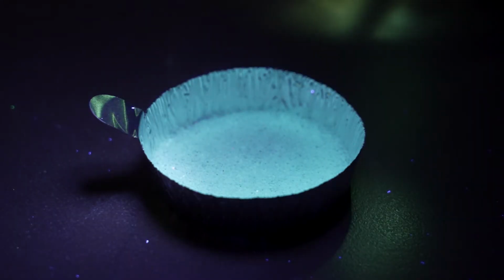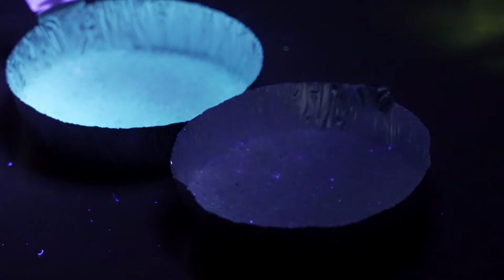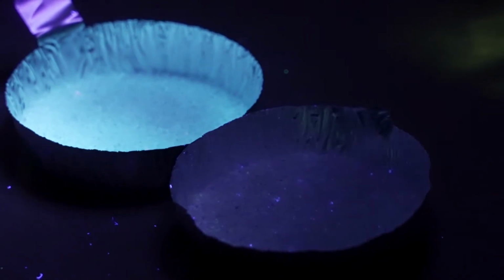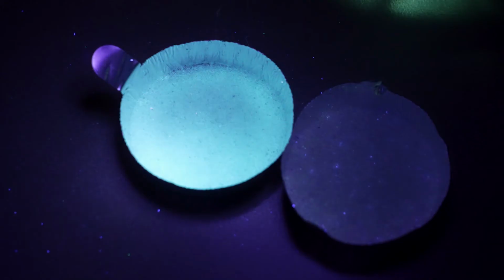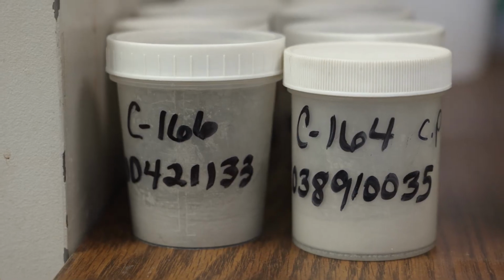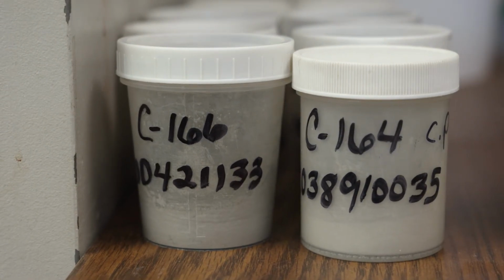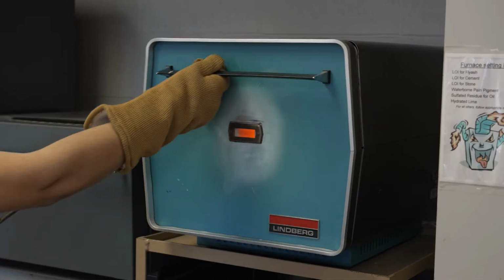We take the beads and we add a chemical called dansyl chloride, and that reacts with the coating. And that reaction causes a product that glows under UV light. So after the test is completed, we put the beads under UV light, and if the beads glow, the adherence coating is present.